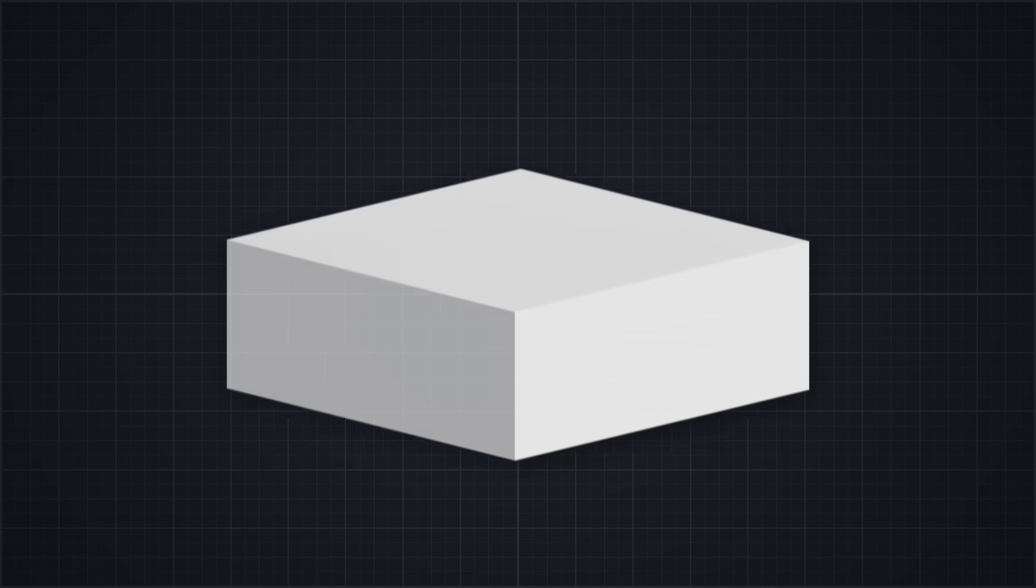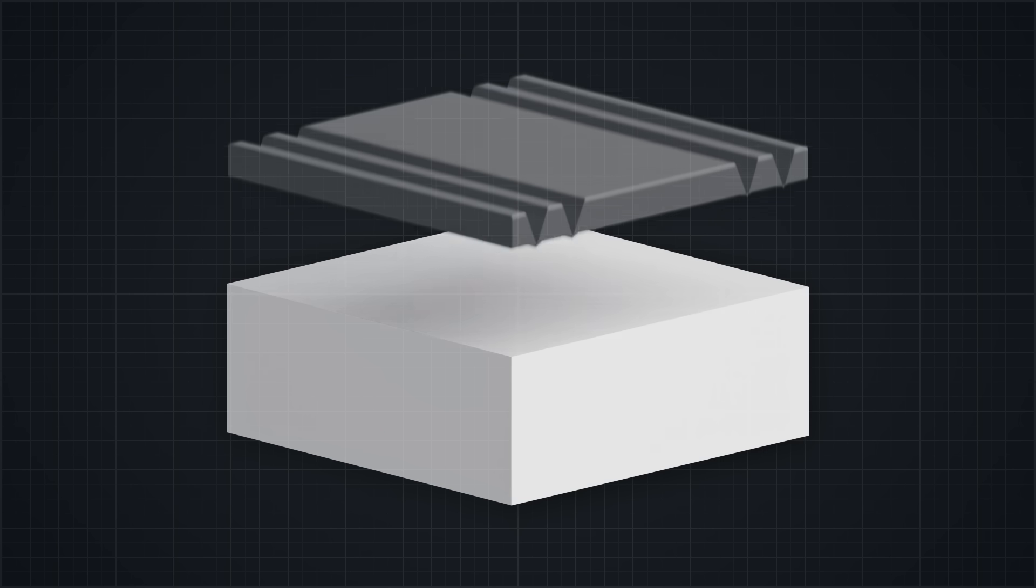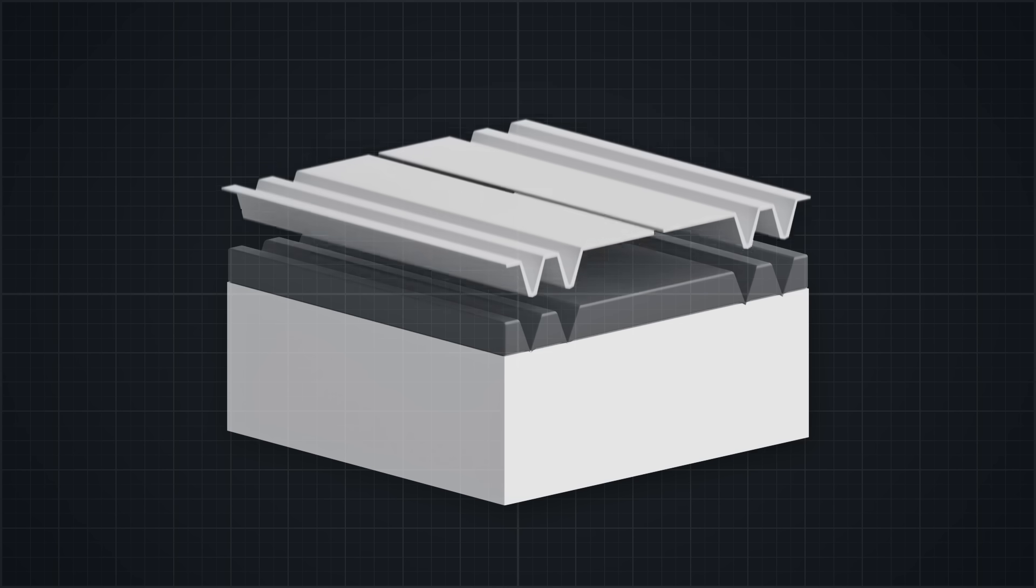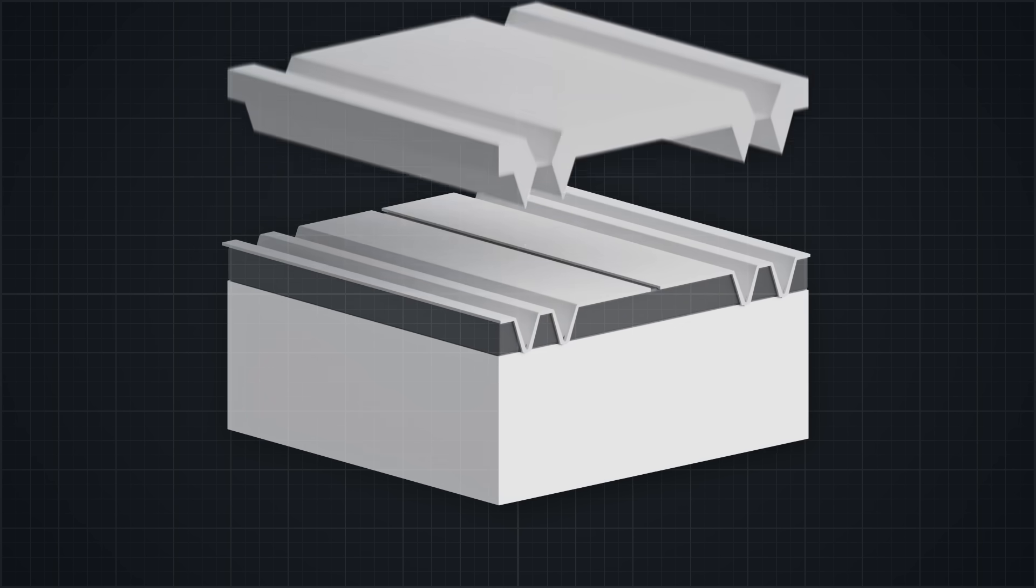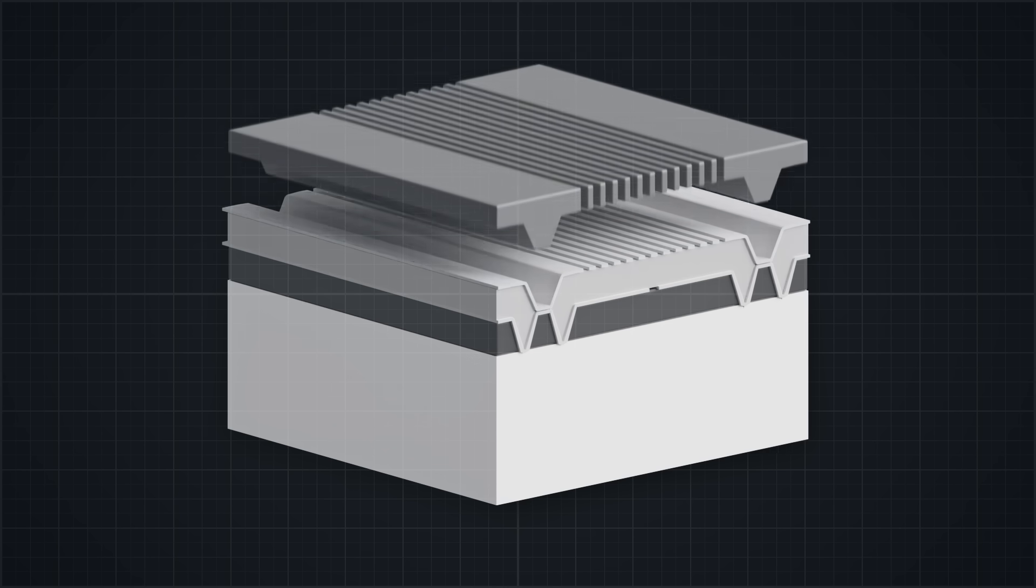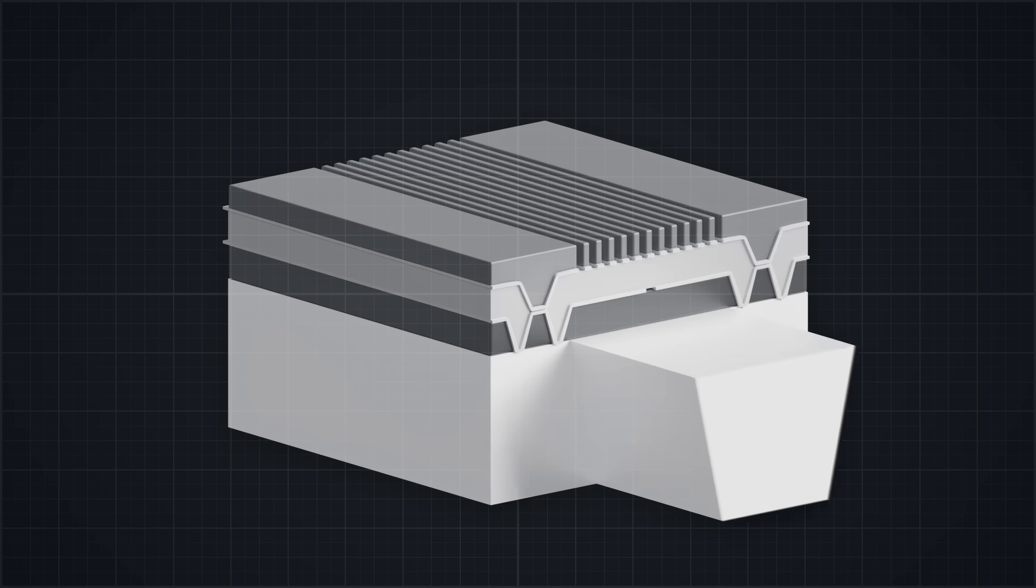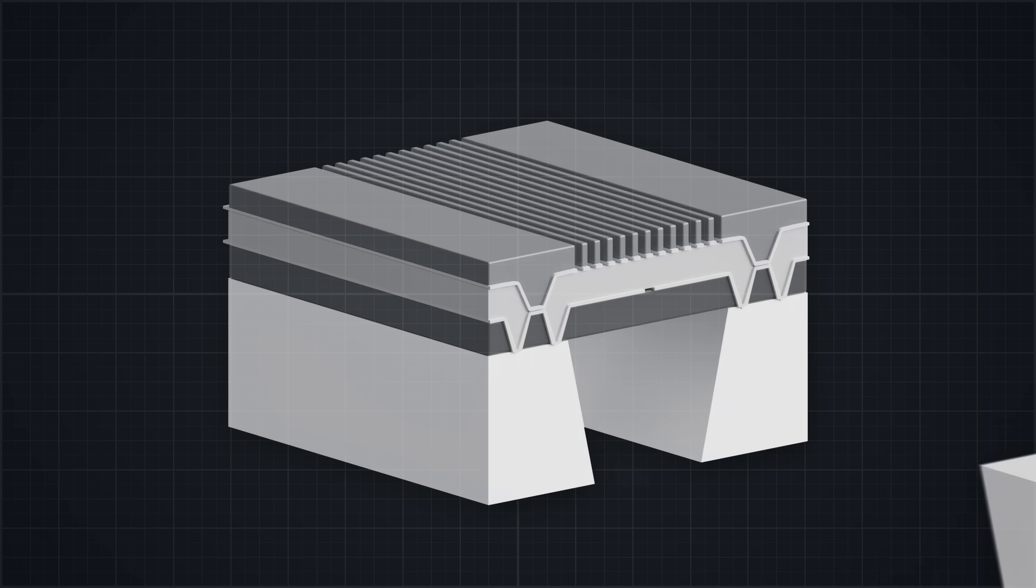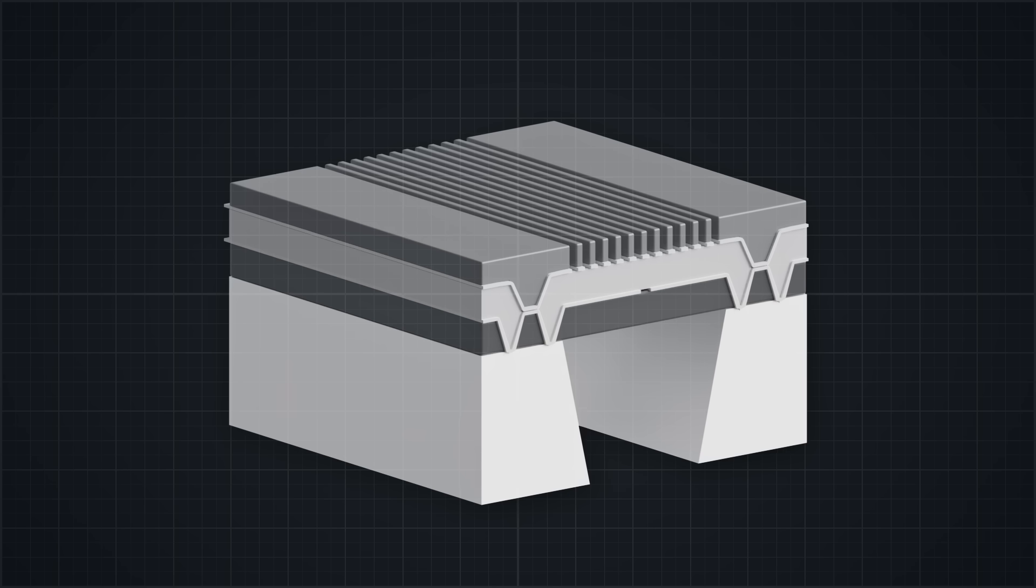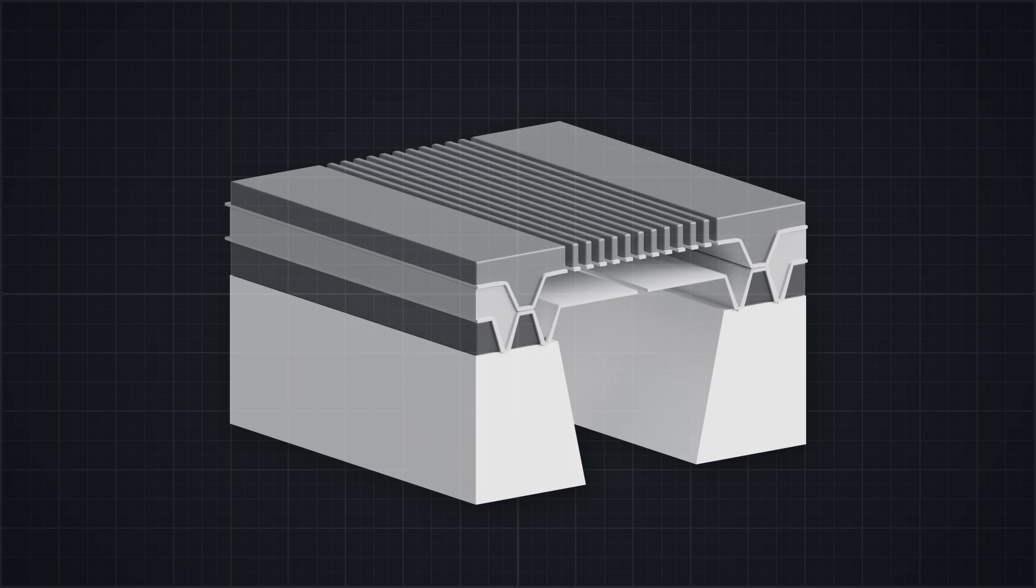The process starts by creating the microphone membrane. First a temporary sacrificial layer made of silicon oxide is added to the surface. Then a thin layer of silicon nitride or polysilicon is deposited on top. This forms the diaphragm, a flexible membrane that will eventually respond to sound. Next comes the creation of the cavity beneath it. This is done through tiny access holes that let the etching solution reach the substrate. The result is a clean hollow chamber that channels sound toward the diaphragm. Then the silicon dioxide sacrificial layers are dissolved away.